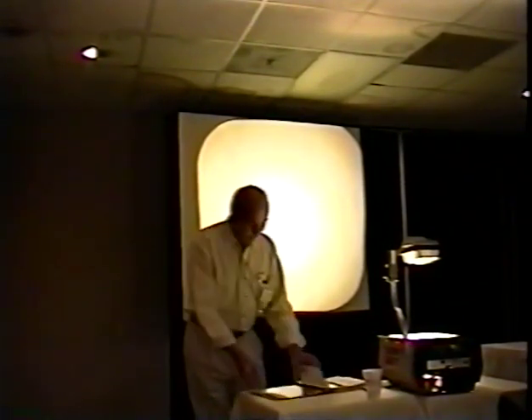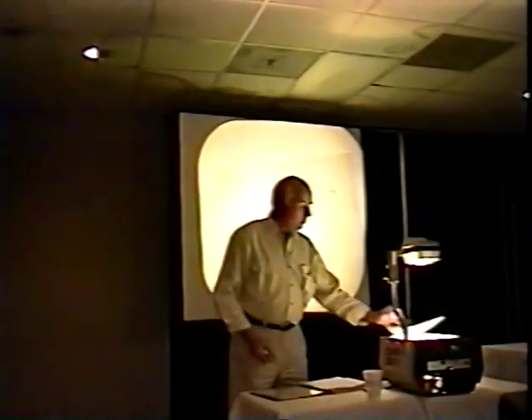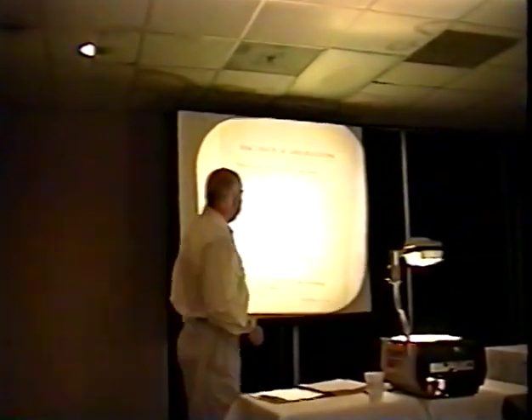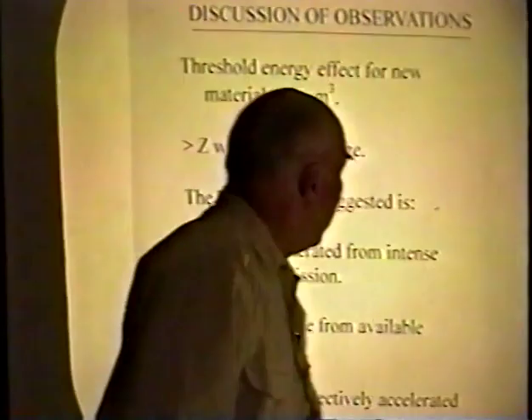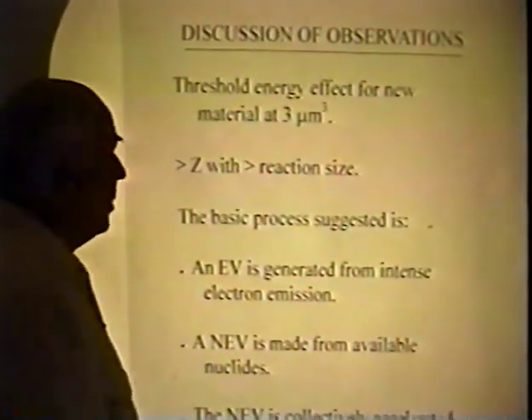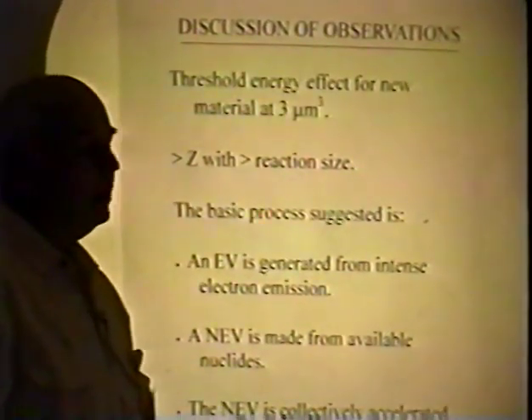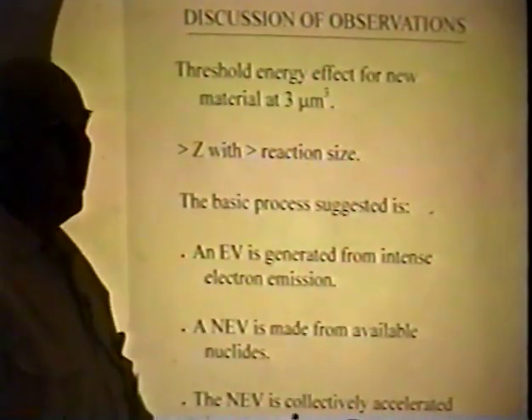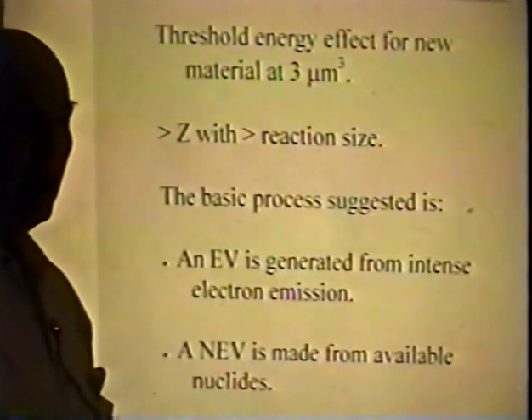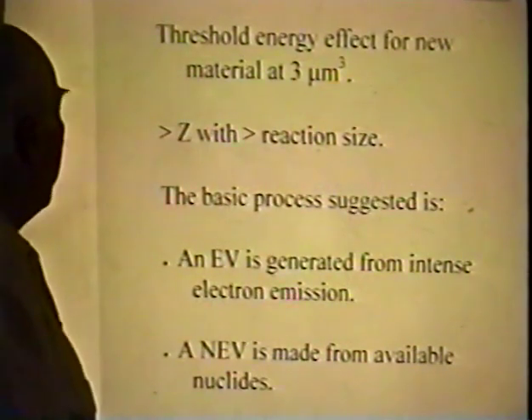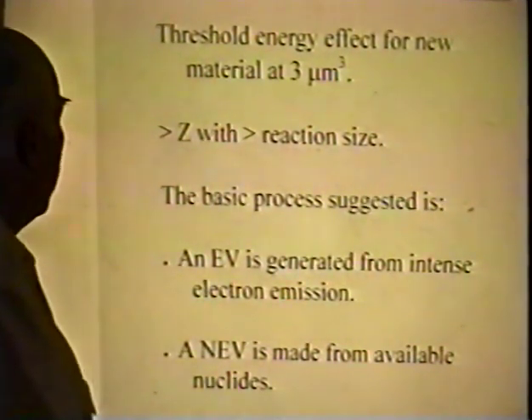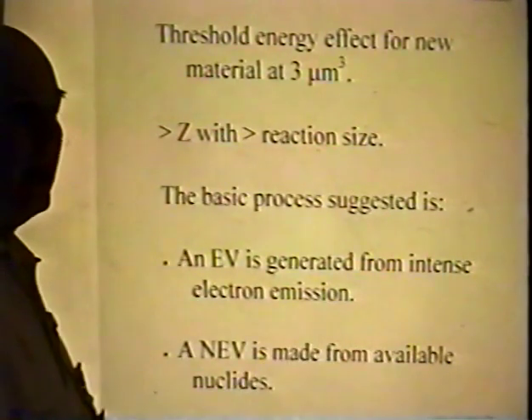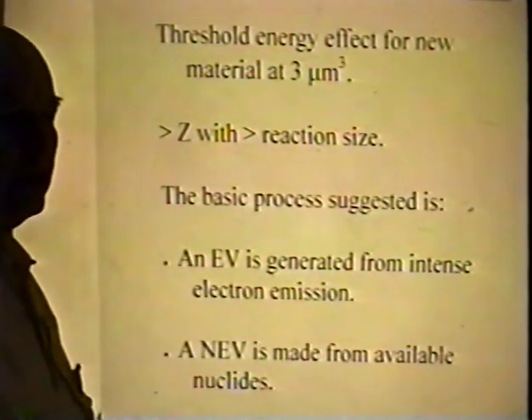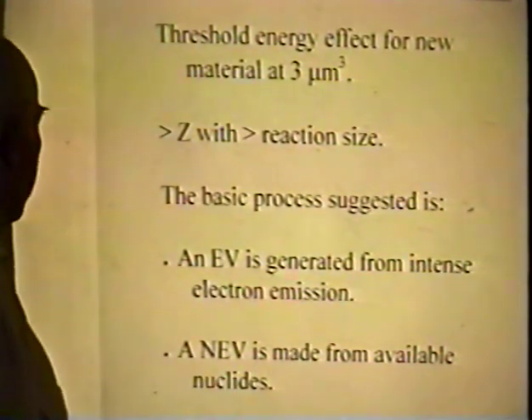EVs directly. So we have seen that there's a threshold effect that occurs around 3 cubic micrometers of material. If you go below that, we don't see it at the energy densities we've got. If you go to higher energy density, then you'll get it. As the reaction size goes up, the atomic number that we see on the products, new products generated, also increases.